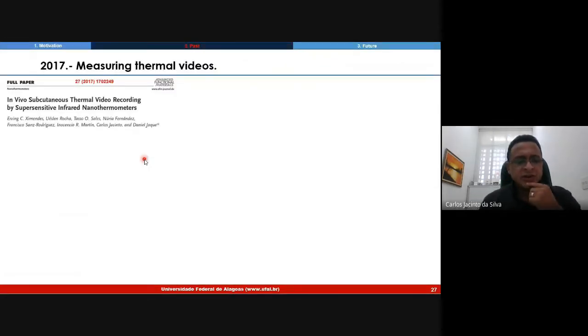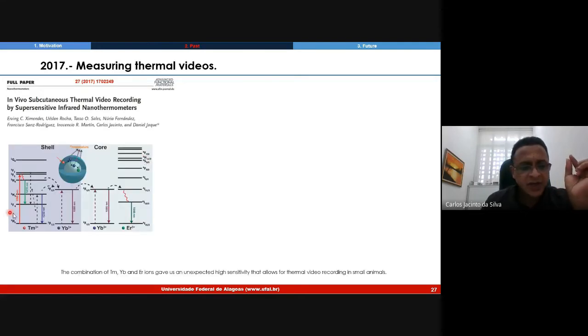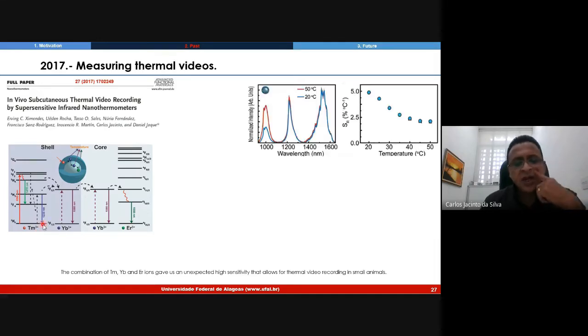Using a core-shell engineering with the combination of thulium and erbium ions, exactly erbium in the core and thulium in the shell, gives us an unexpectedly high thermosensitivity that allows thermal video recording in small animals. For the luminescence nanothermometer, we use the emission of the erbium at 1,000 nanometers and the thulium at 1.2 micrometers, or thulium and the erbium at 1.55 micrometers, obtaining super sensitive